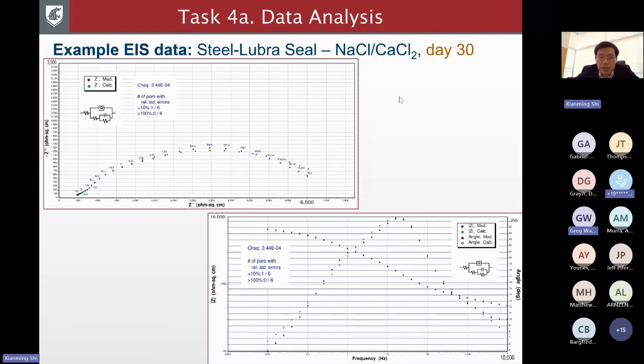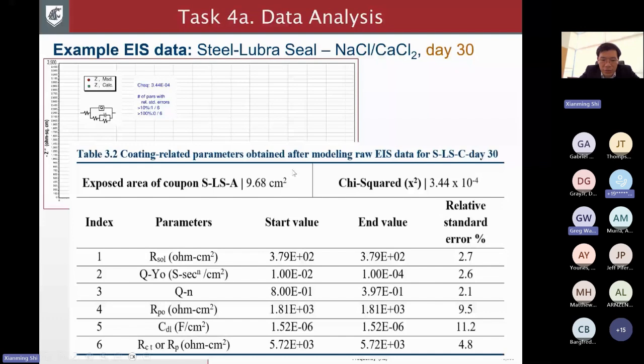So this is just one example, a steel coated by Lubra Seal, in this sodium chloride and calcium chloride mixture de-icer at day 30, with all the EIS results, and then we can derive these parameters. Again, the most important thing we want to look at here is this Rpo, which is the pore resistance. Basically, the coating under a microscope is highly porous, even though to our naked eye it looks very impermeable. So the de-icers penetrate and saturate that coating, and over time this resistance drops, and that's an indication of the coating failing over time.